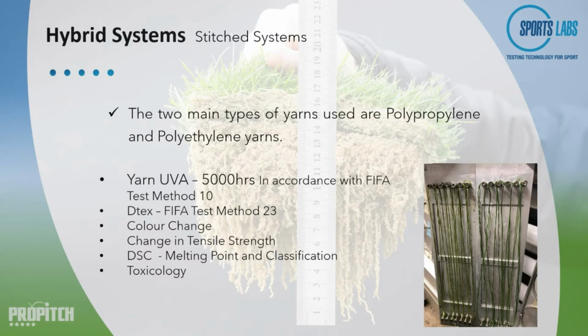We can test it for UV exposure up to 5,000 hours, same as previously mentioned, where we measure the change in tensile strength and colour change after the 5,000 hours exposure. We can then measure the dimensions of the yarns and their melting point in the DSC machine to ensure it matches the information in any corresponding UV test report if there's one available. We can also measure the yarns for toxicology, as per the textile-based systems as well.